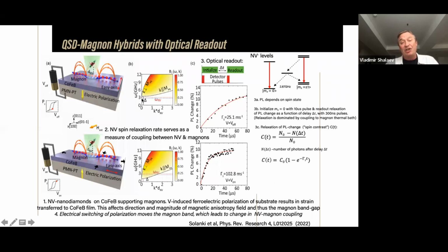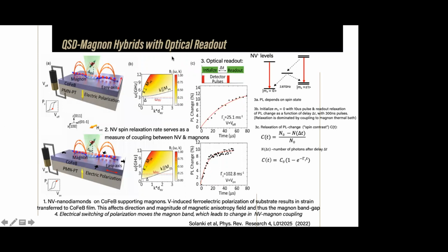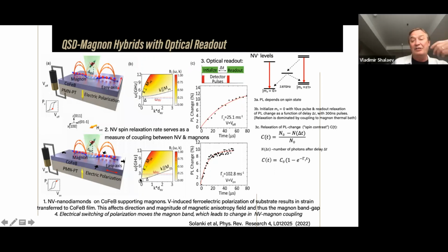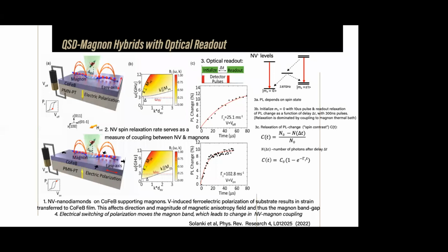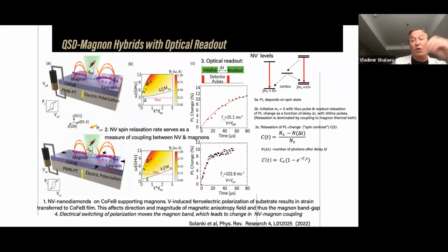So let's say if initially the magnon band was above the resonance of your electron spin, then basically there is not much coupling between electron spin and magnons. But if you now apply voltage and move the magnon band, then now the spins start to interact with each other via these magnons. So you could switch on and off your interaction between qubits by basically applying voltage. And you read it optically by looking at the relaxation time. And indeed, we showed when there is no coupling to magnons, then the relaxation is slow. And when there is a coupling, then the relaxation is fast, indicating that there is very strong spin-magnon coupling.